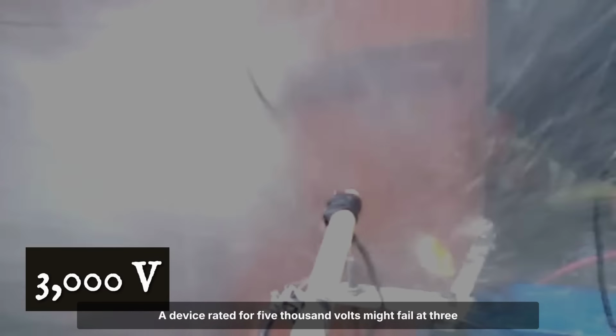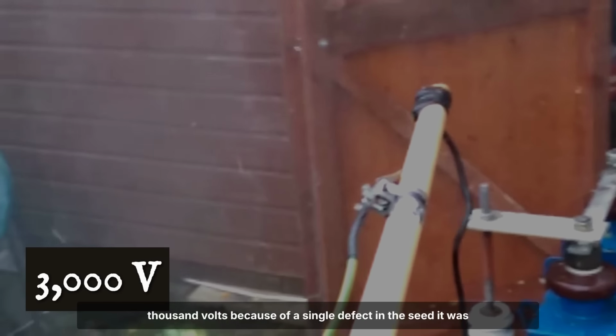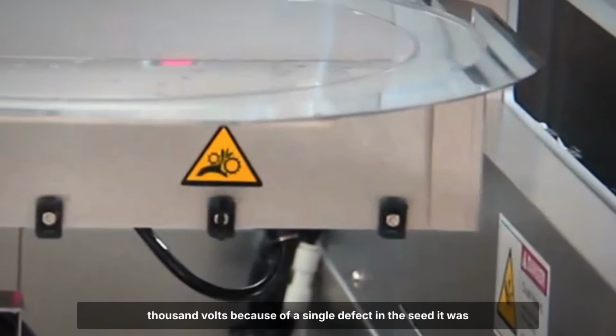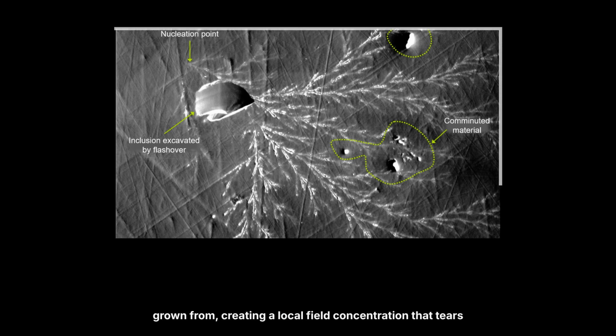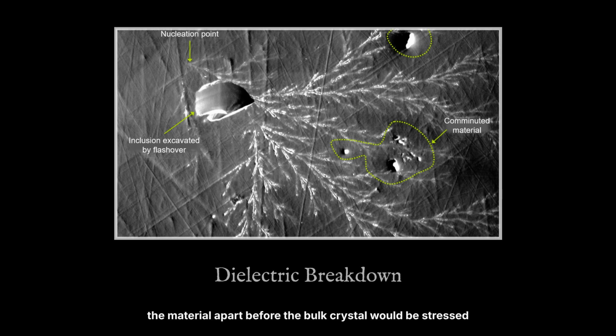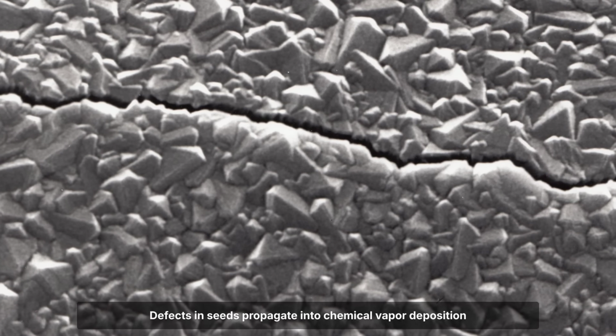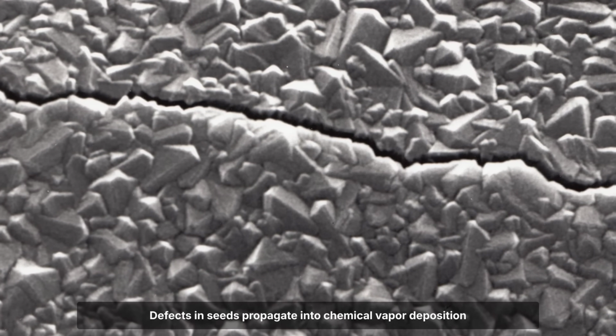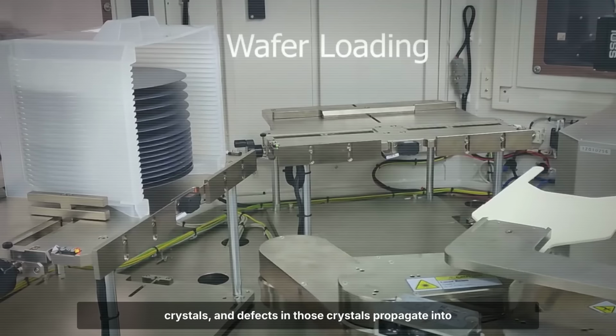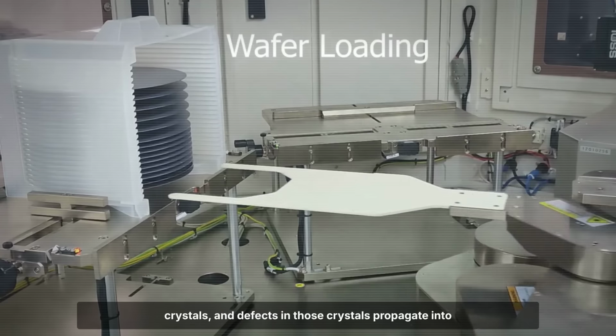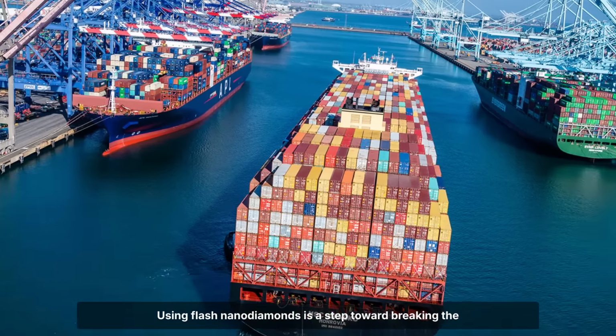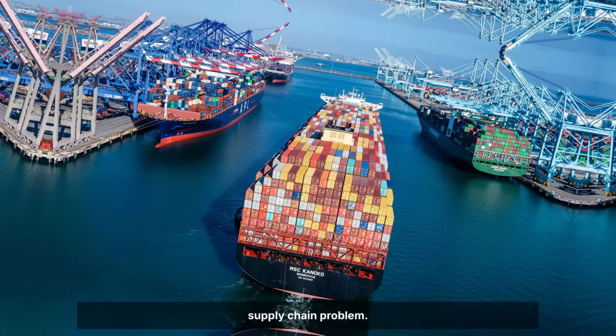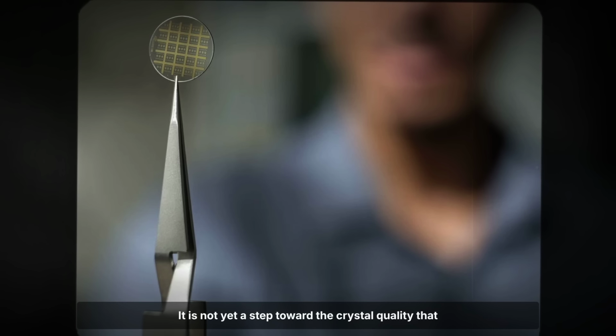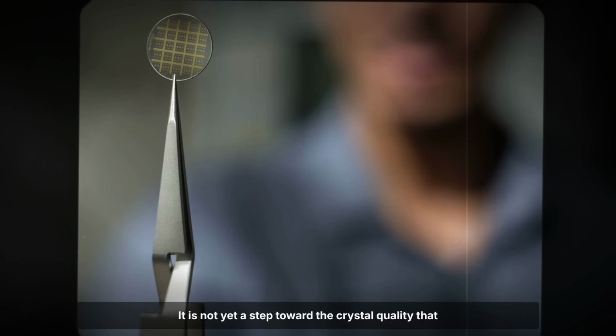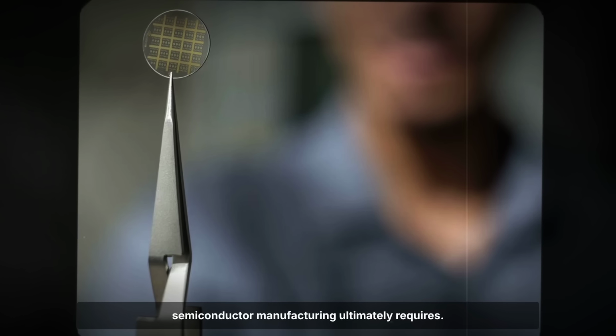A device rated for 5,000 volts might fail at 3,000 volts because of a single defect in the seed it was grown from, creating a local field concentration that tears the material apart before the bulk crystal would be stressed at all. Defects in seeds propagate into chemical vapor deposition crystals, and defects in those crystals propagate into devices. Using flash nanodiamonds is a step toward breaking the supply chain problem. It is not yet a step toward the crystal quality that semiconductor manufacturing ultimately requires.